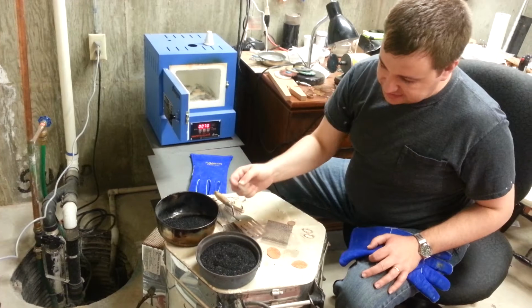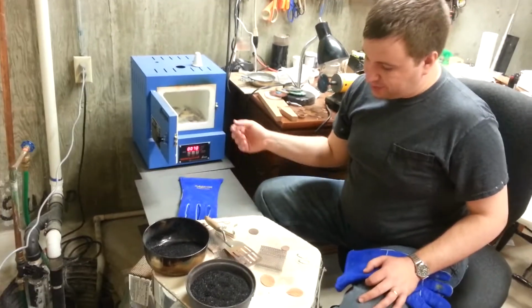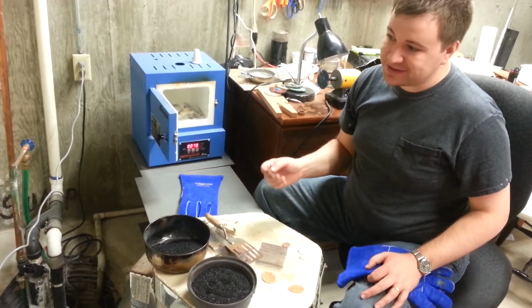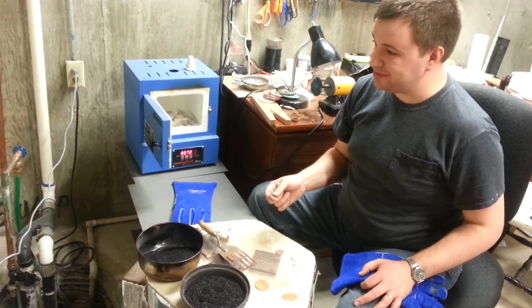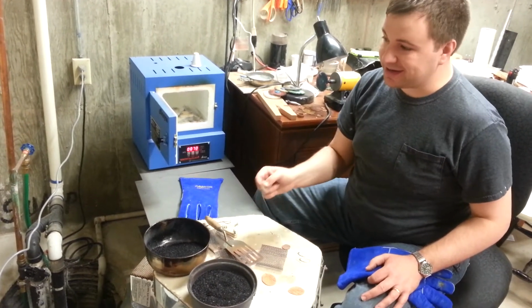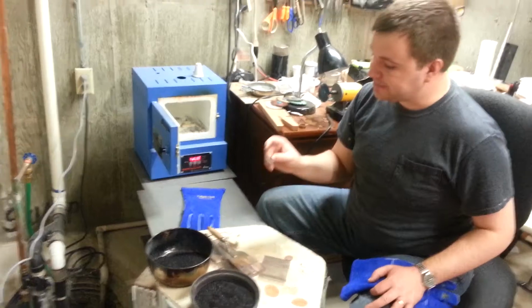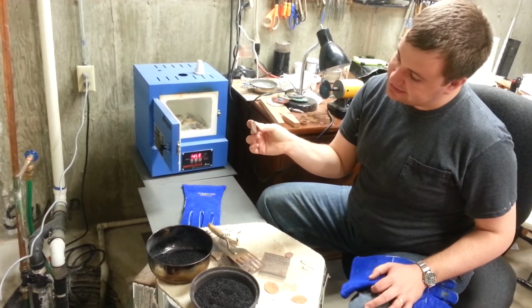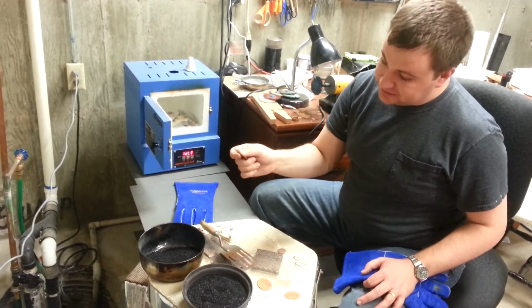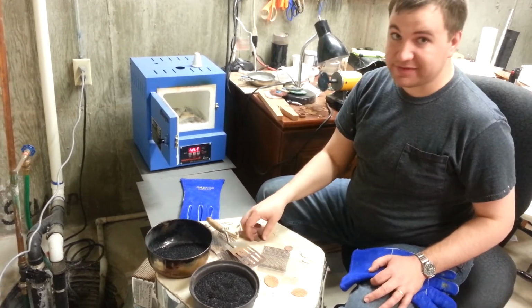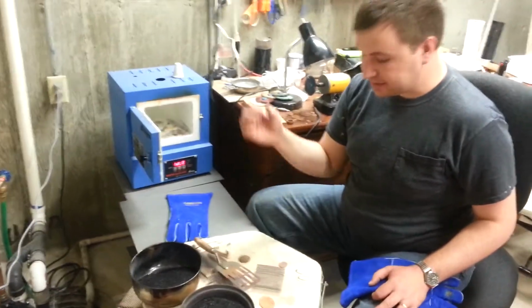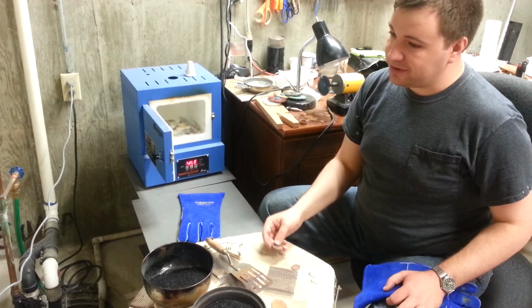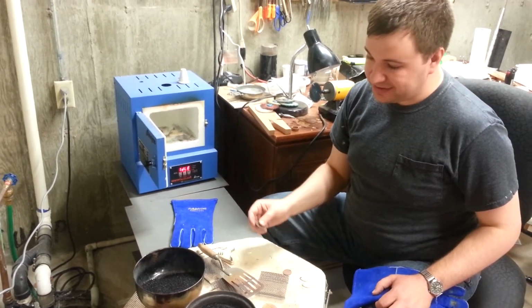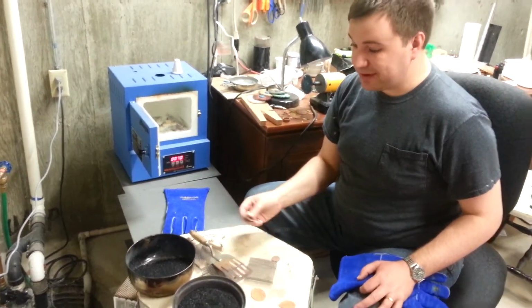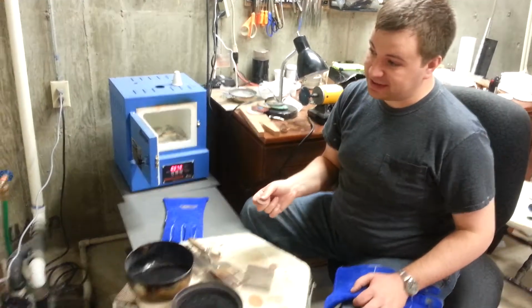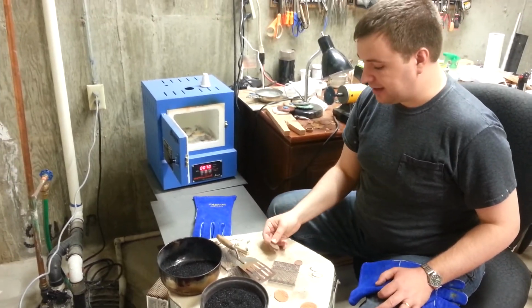The first test I do, you can quench them in water. If they're not completely sintered, that will usually destroy them, so I don't usually do that because you can try again by firing again sometimes. But the first test to see if it works is to see if it makes a metallic sound. If it's kind of a thud or if it's not really tingy, it probably didn't work, and you probably should try firing again, maybe at a little higher temperature.